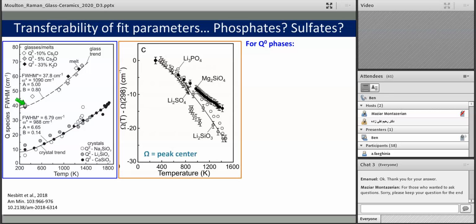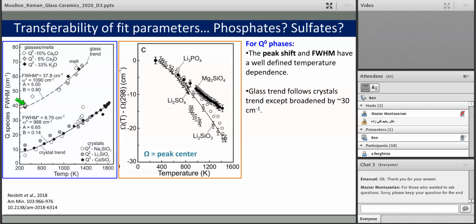To show that this is even more broadly applicable, and not just a simple fact that we've chosen some nice systems here, this normalized shift in terms of the peak center relative to that at ambient conditions. Here we have this normalized plot, including silicates such as magnesium orthosilicate and lithium metasilicate, but also a lithium orthophosphate and lithium orthosulfate. So it turns out, although there's a bit more spread in this data, there is a very consistent peak shift with temperature, and similar trends are found with the full width half max of these phases, although in the case of the full width half max, they follow slightly different trends here.